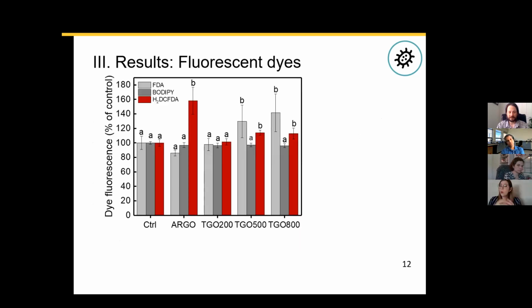Now we're going to shift the question that we have. We know that these materials are showing some toxicity, but we want to change the question from whether these materials are toxic to how they elicit that toxicity. So we did a set of fluorescent dye-based assays, using 3 different fluorescent dyes, each indicating different biochemical responses in the bacterial cells. For example, we have fluorescein diacetate, which is usually an indicator for membrane integrity and esterase activity. We have BODIPY, which is an indicator for lipid peroxidation. And we have dihydrodichlorofluorescein diacetate, which is an indicator for reactive oxygen species generation.